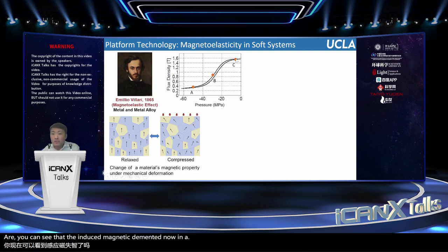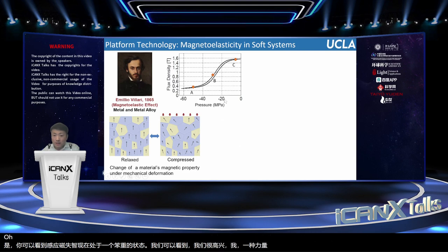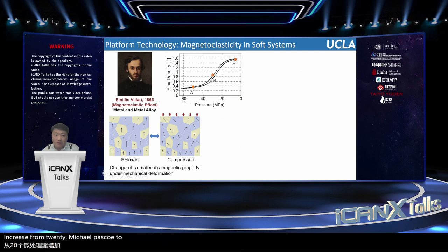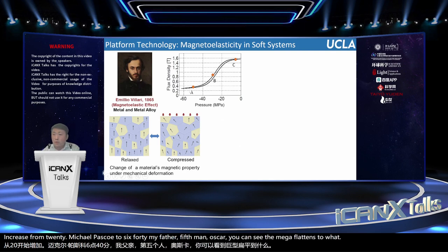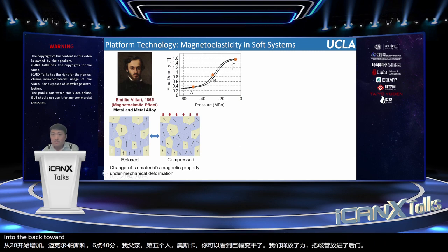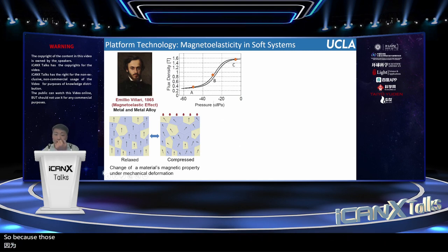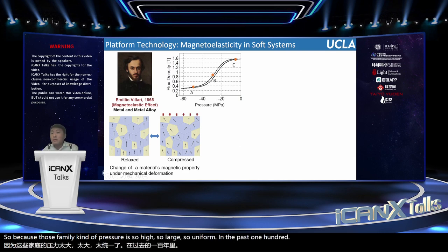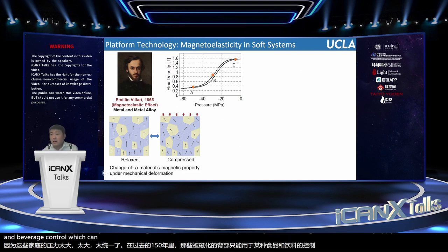So in a bulk state, we can see that when you apply mechanical force, increasing from 20 megapascal to 40 megapascal to 60 megapascal, the magnetic flux density will decrease. When you release the force, the magnetic flux density goes back to the original state. Because the biomechanical pressure required is so high, in the past 150 years those magnetic effects could only be applied to some kind of building vibration control, which has huge mechanical pressure.